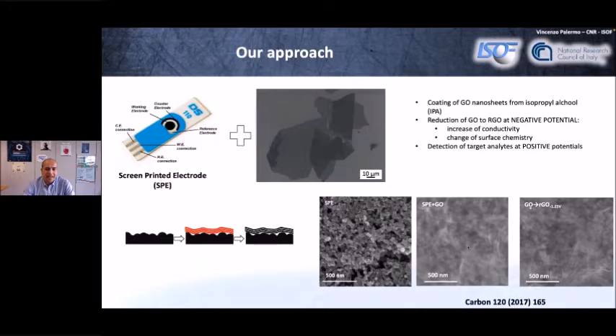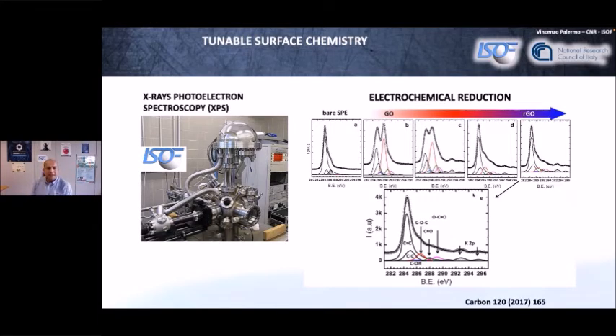Then for the detection of the analyte, the sensor works at positive potential, so you don't modify your electrode anymore. And as you can see from the electron microscopy images, not much changes. The surface remains flat with these small ripples that are due to the large sheets that have been deposited on top. But when you do the reduction, of course, the chemistry changes a lot. And you can follow this with a special technique called X-ray photoelectron spectroscopy. I will not go into details of this, but this technique can really measure on the surface which kind of atoms you have, if you have carbon, iron, silicon, oxygen, whatever, but also the type of chemical bonds that are on the surface.